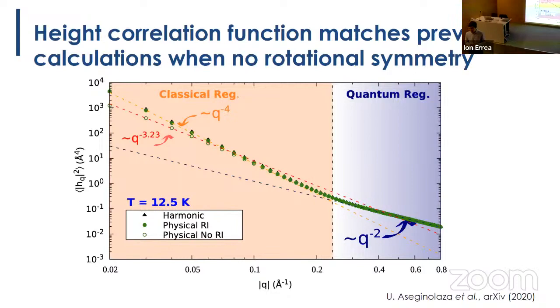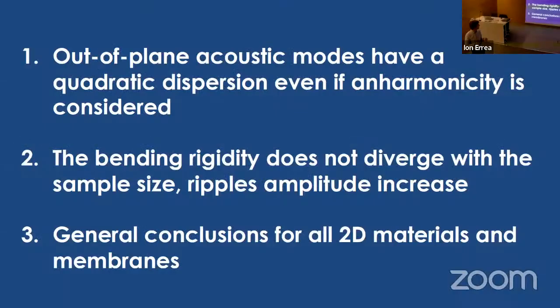So we believe that, in consequence, the classical interpretation that the bending rigidity has to diverge in the long wavelength limit is not correct. Somehow the amplitudes are bigger the bigger the sample, but the bending rigidity is the same. This is our interpretation of this story. So in conclusion, out of plane acoustic modes have a quadratic dispersion, but this still allows the propagation of sound. I am very happy with this result. We've been struggling to publish this, but I am very happy with it.